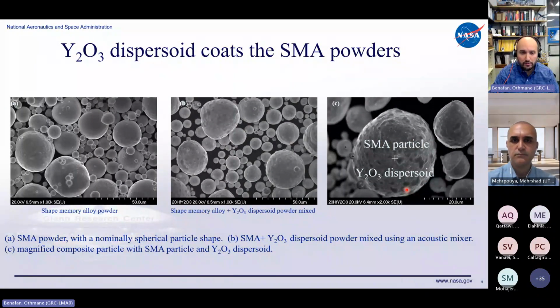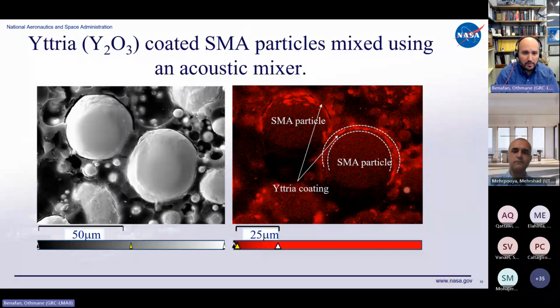The same concept is used for hafnia or other things. But you can see here, number one, can you coat the powder? Can the dispersoid adhere to the SMA powder before you start any additive manufacturing, as a check? And from this data, it looks like we are achieving that, as was achieved in other alloys like I showed you on the nickel-based superalloys. If we dive a little more with a couple more SEM images, these are particles doped with yttria. In this particular angle, you can see how the yttria is decorating the SMA particle. The SMA particle is in the middle, and yttria is going around it here, and we're missing the image on this part.